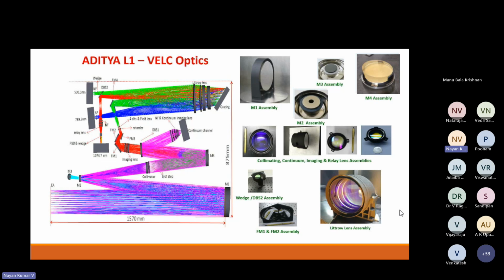This was a real challenge, and we had to develop certain polishing technologies. This was done on a Zerodur base material. Inherently, being a glass ceramic, it is very difficult to achieve very high accuracies. What is reported in literature is for very small samples of around 25 mm, where one can reach around 1.2, close to 1, like that.